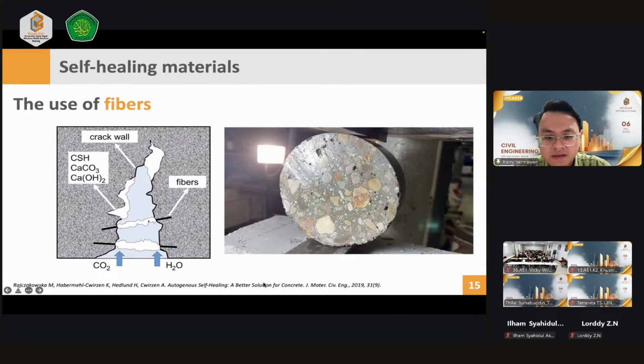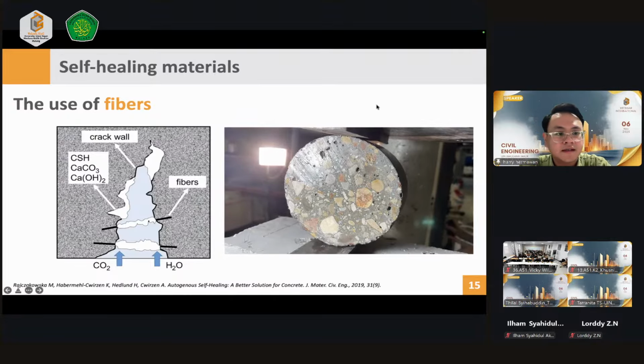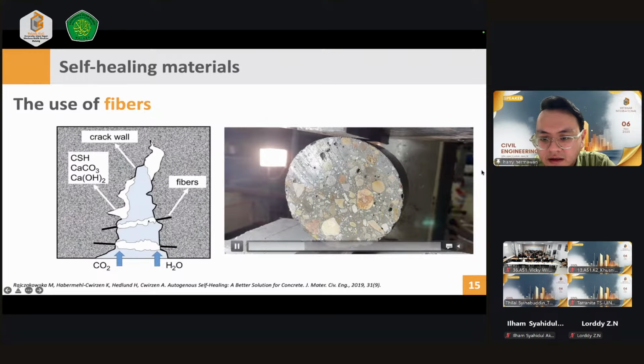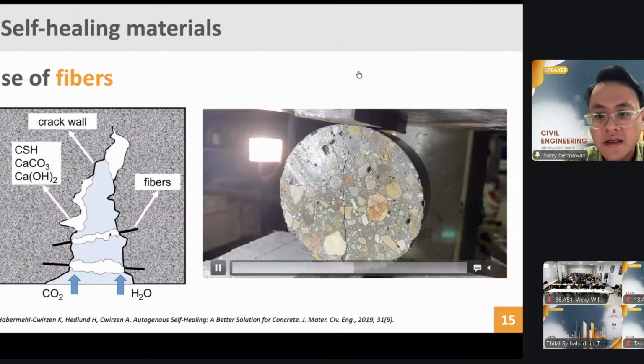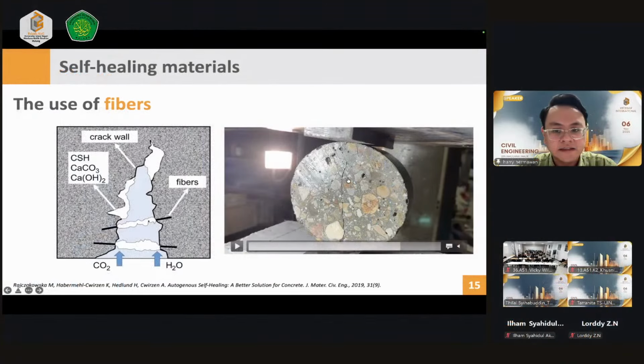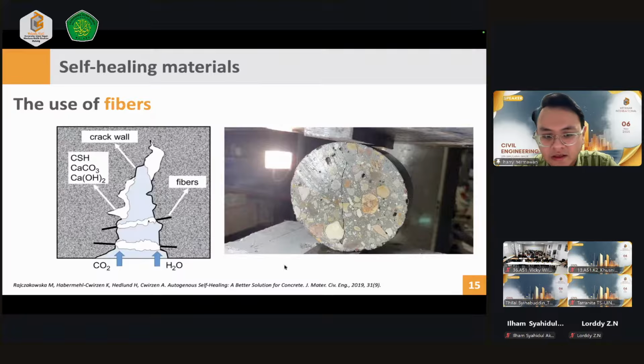This is a video that I have prepared in advance. I will try to play it. I hope it works. If you look here at the concrete specimen, I have incorporated fibers inside, and when I subjected this specimen to the Brazilian splitting test, the concrete did not fail directly, but generated a single crack. The crack also starts from a micro size, and then it grows slowly until a certain width.